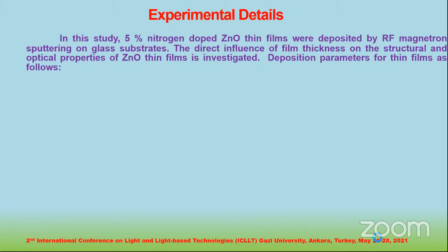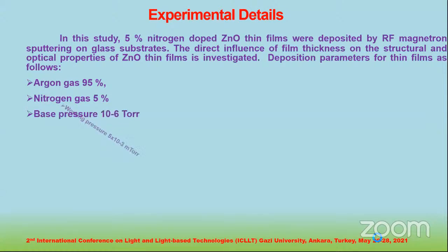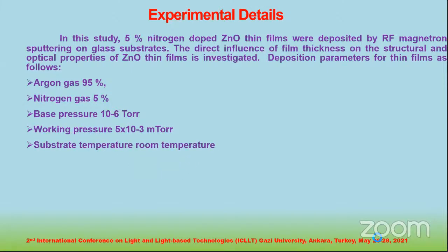The direct influence of film thickness on the structural and optical properties of zinc oxide thin film is investigated. Deposition parameters for thin films are as follows. Argon gas 95%, nitrogen gas 5%, base pressure 10 to the minus 6 torr, working pressure 5 times 10 to the minus 3 millitorr, substrate temperature, room temperature.